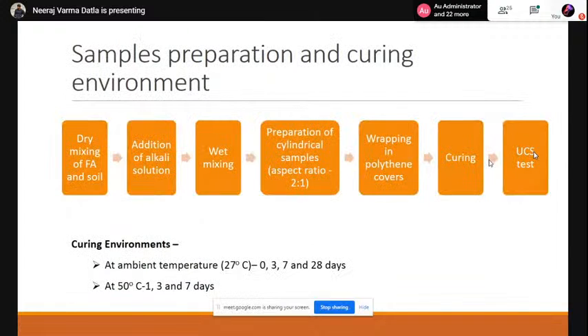And this is the sample preparation. First, we dry mix the fly ash and soil. Then after adding alkaline solution, we wet mix until we get a homogeneous mixture. Then we prepare a cylindrical sample with an aspect ratio of 2:1. To avoid moisture variations during the curing period, we wrapped the samples in polythene covers. Then after the particular curing period, we went for UCS testing.